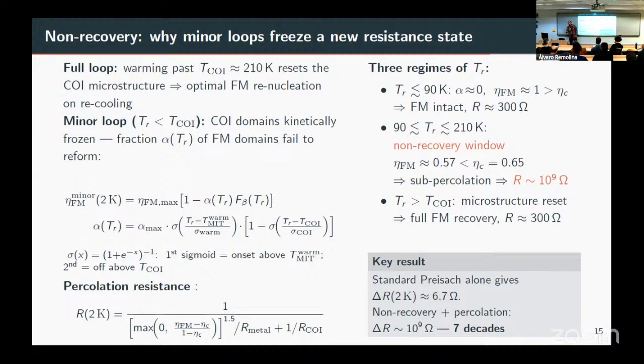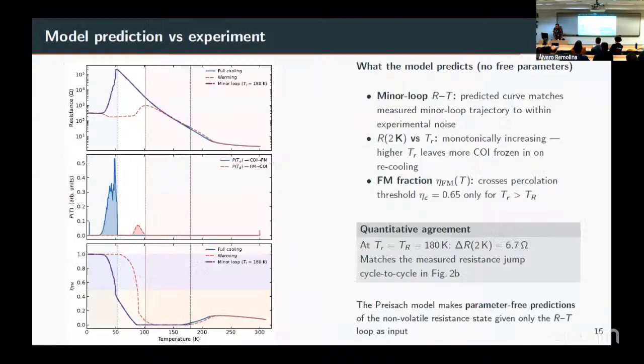And then I can include the fact that when I go very low in temperature and apply a current pulse, or when I go down in temperature and come back, I'm not allowing all the domains to switch back. So I end up with a system that is more insulating, because there is no percolation threshold anymore, compared to when the sample is at equilibrium.